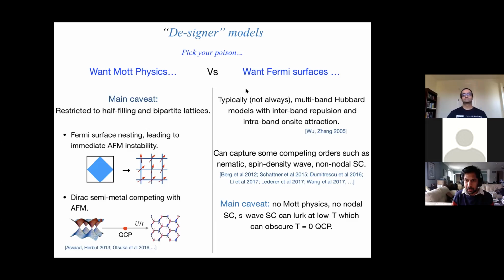So at least I would like to separate sign-problem-free models into these two classes, where in one case you can have local repulsion, so you can have a well-defined local moment, so you can access, for example, a near antiferromagnet. In this case, you can't, because essentially, when you integrate out any kind of electrons, you will generate an attractive Hubbard U for the same band. And the issue with this class of systems is you will never be able to get nodal superconductors, and that you can check in any of these models. The nodal superconductor is not possible. You can get a lot of other interesting things, and that's why we do it. But here I'm interested in getting nodal superconductors.